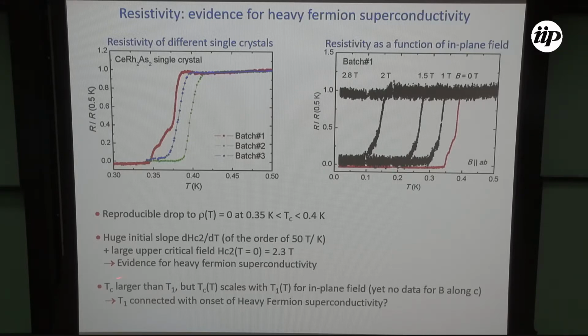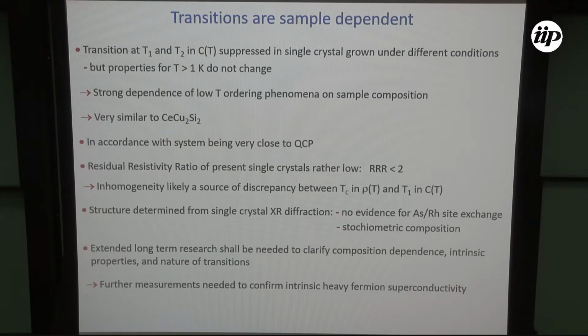The problem we have is that Tc is a little bit below T2, seen in the specific heat, but larger than T1. But what we observed is that this transition temperature scales with T1 for in-plane applied field. We have as yet no data for B along c, that is just being done. And therefore, that would be an indication that T1 is connected with the onset of heavy fermion superconductivity. But we certainly have to confirm that.